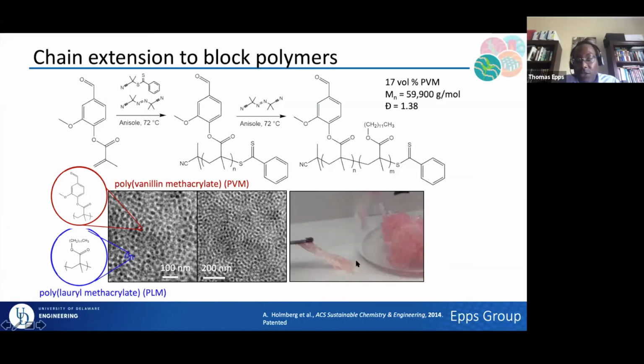And then when we take that material, and I won't focus too much on this now as I have another example later on, this has a nice tackiness to it, which has a consistency that's very similar to the back of sticky notes. And we actually have a company that's licensed this material and is interested in using it. I will mention that the color is from the chain transfer agent, which is pink. We can burn that off at about 85 degrees Celsius and then get a nice clear material. It just didn't give as good a picture, so we left it in there for artistic license here.